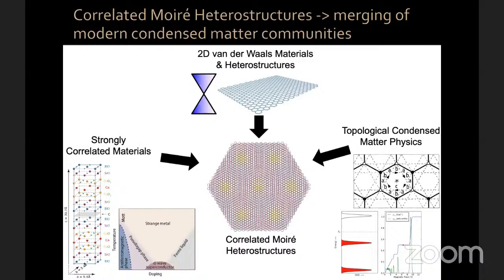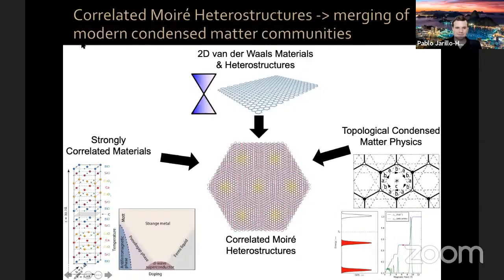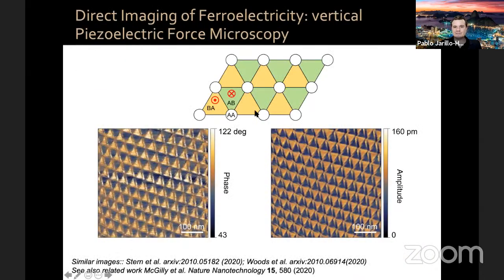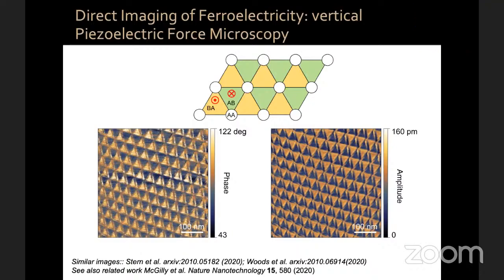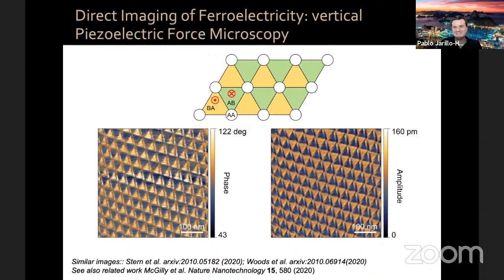Another short question about the ferroelectricity. In the ferroelectric system with two hBN, in that case there is no magic angle, right? You mean there is a continual situation where you have those domains, right? That's right. You will not have domains if you have exactly 0 degrees, but it will be ferroelectric. The entire system will be AB or BA stacking. If you have a little bit of an angle, you will have AB and BA domains, and you will also be ferroelectric. Only if you go 180 degrees, you will not have ferroelectricity. I see. Well, that's very nice. Thank you very much, Pablo. Then hope to see you soon here. I hope so too. Bye.